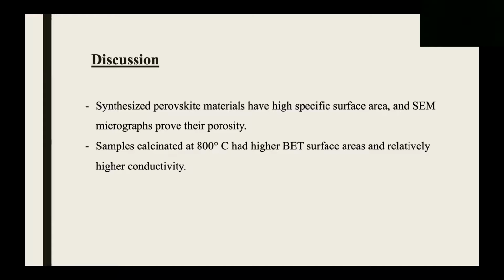And now we are working on the conductivity measurements at higher temperatures, and we are expecting that the electrical conductivity will increase with the increase in the reaction temperature, actually. And considering our catalyst, the samples calcinated at 800 degrees Celsius have higher surface areas and a relatively high conductivity.